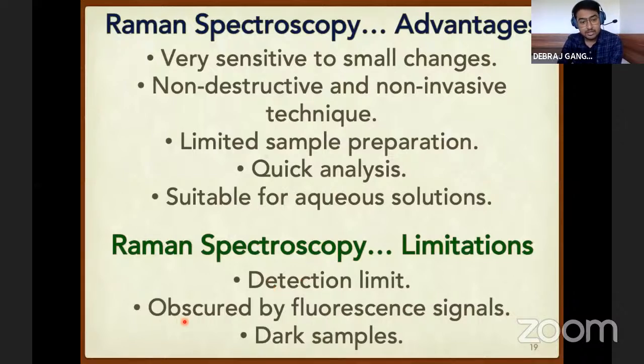Another thing is that it is obscured by fluorescent signal. So if there is fluorescence in the sample, the fluorescence will overcome the Raman bands because the Raman bands are weak. And for dark samples also, it is very hard to record the Raman spectrum.